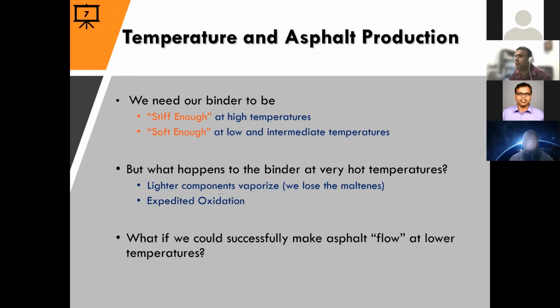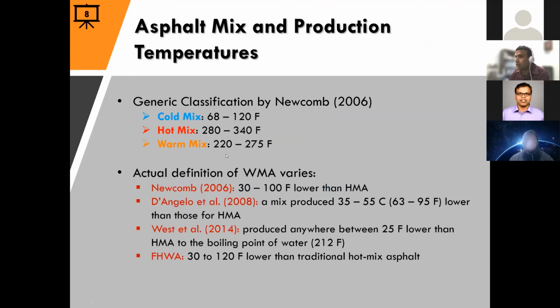But what happens to binder when we heat it to very high temperatures? We lose the lighter components, which is basically the maltenes, and we expedite the oxidation. So isn't it obvious that if we could achieve at a lower temperature everything that we achieve by heating the asphalt to a very high temperature, it would be better? Of course, I am aware of the aggregate drying, aggregate moisture removal and everything, so we'll get to that. But if we achieve that, is it better, right? So let's take a look at it.